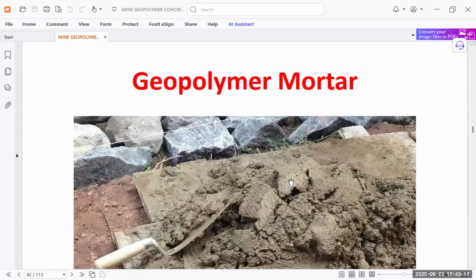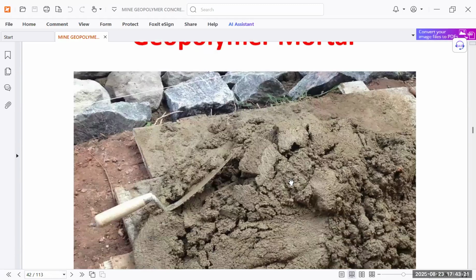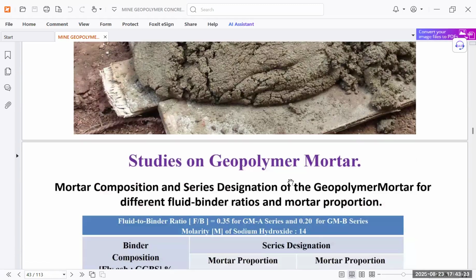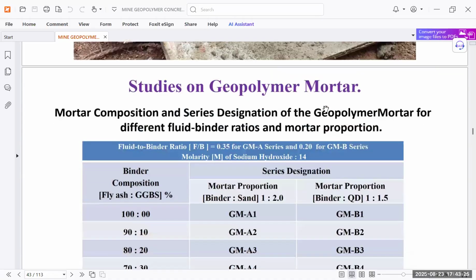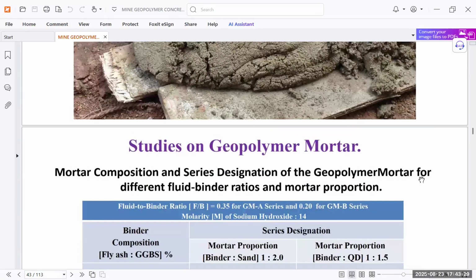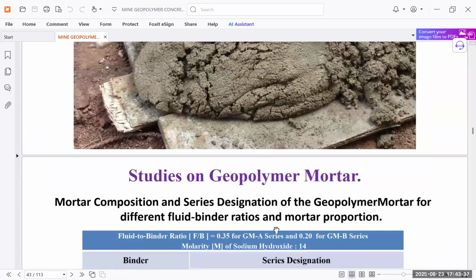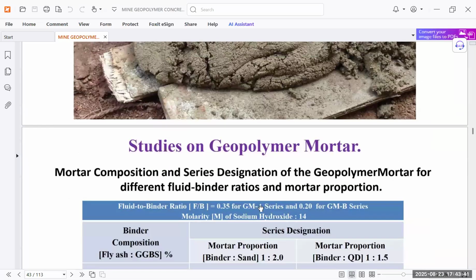So now geopolymer mortar, like we have discussed, we have made something like this. Studies on geopolymer mortar are also done. After these studies, the mortar composition and series designation of geopolymer mortar for different fluid binder ratios were made, because we are using the fluid binder ratio here, not the water cement ratio. That is why we have now changed the fluid binder ratios and mortar proportions. Fluid to binder ratio is 0.35 for the GMA series, and we have taken 0.2 for the GMB series.